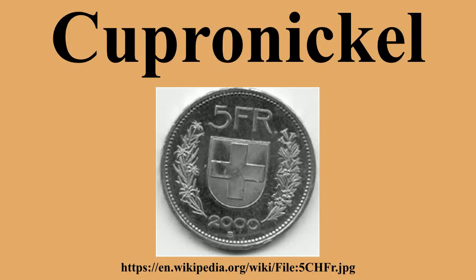The theory of Chinese origins of Bactrian cupronickel was suggested in 1868 by Flight, who found that the coins considered the oldest cupronickel coins yet discovered were of a very similar alloy to Chinese paktong. The author scholar Ho Wei precisely described the process of making cupronickel in about 1095 CE. The paktong alloy was described as being made by adding small pills of naturally occurring Yunnan ore to a bath of molten copper. When a crust of slag formed, saltpeter was added, the alloy was stirred and the ingot was immediately cast. Zinc is mentioned as an ingredient, but there are no details about when it was added. The ore used is noted as solely available from Yunnan.